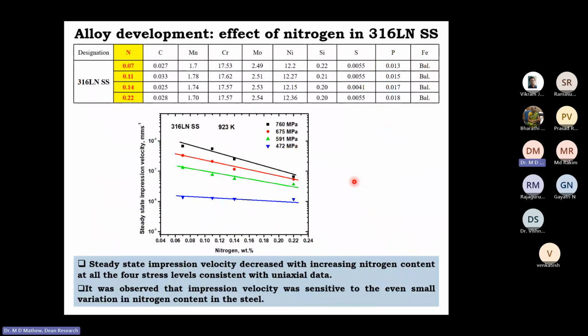Yes, this is coming back to our alloy development program, where creep tests are always very long. In fact, IGCAR has the record of having conducted the longest creep test. It was 1,50,000 hours, close to 20 years. One creep test was continued before it fractured. So we cannot do that kind of creep test for an alloy development program. So we were trying to optimize the amount of nitrogen as far as the creep and fatigue properties were concerned by preparing a number of laboratory heats with various amounts of nitrogen. So this data is about the optimization of the creep properties using impression creep test.